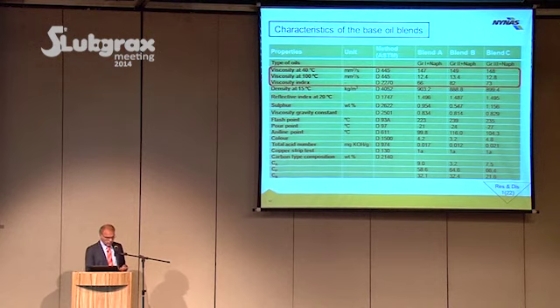What is interesting with these, if you look at the viscosities, of course, we see that the viscosity index differs slightly between these 3 products, depending on the amount of naphthenic oil which has been used, and the starting viscosity index for the paraffinic oil. Since, as you know, naphthenic oil always has a lower viscosity index than paraffinic oil. However, my question very often to the grease maker is, what is a sufficient viscosity index? What is good and what is poor? 100, 95? In hydraulics, viscosity index is very important. In grease, it's not as important as that.